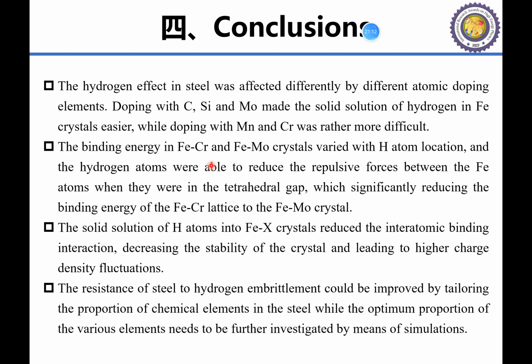The solid solution of hydrogen atoms into Fe-X crystals reduces the atomic binding interaction, decreases the stability of the structure, and leads to high charge density fluctuations. And finally, the resistance of steel to hydrogen embrittlement could be improved by tailoring the proportion of hydrogen-affecting elements in steels, while the optimal proportion of the various elements needs to be further investigated by means of simulation.